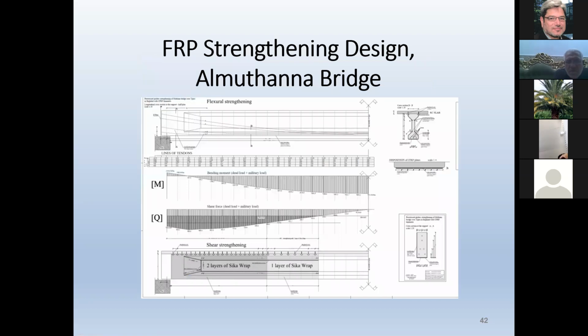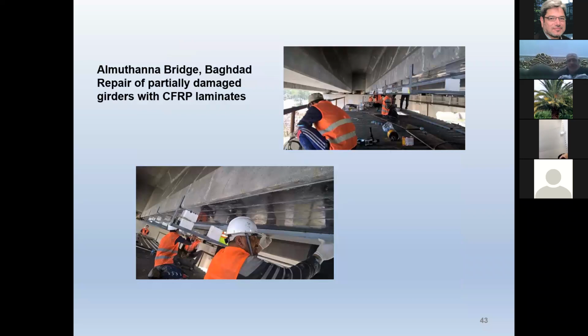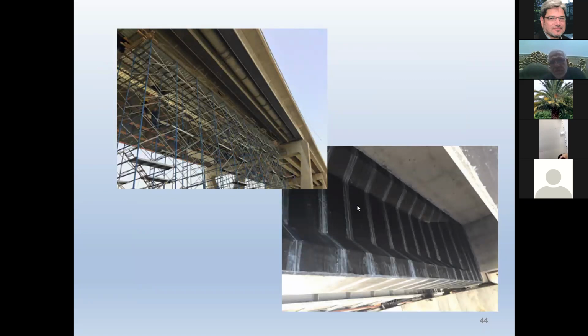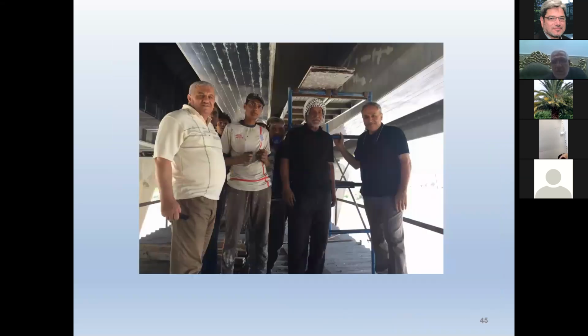Now, for the girders that were partially damaged, we developed a strengthening system to reinstate their flexural strength as well as their shear strength. And this is something that we trained many workers in there. They were trained to apply the FRP, local workers, and it was done in record time. As you can see here, this is shear strengthening, the vertical sheets here. And at the bottom here, there were a lot of strips of FRP laminates to reinstate the flexural capacity of these girders. This is after the completion of the work that was done a number of years ago.